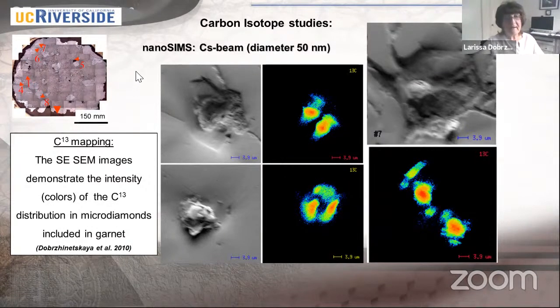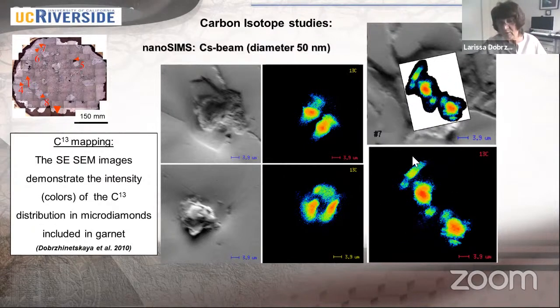So we go with this sample first to NanoSIMS. NanoSIMS has a cesium beam with a diameter of 50 nanometers. And you see here carbon 13 mapping. You see here different intensity of the color. It shows how intense carbon 13 is in these particular diamond crystals, okay? So you see here this part of the elemental mapping we put on this diamond, and it exactly shows the area where the delta 13 distribution shows us the intensity of these parameters.